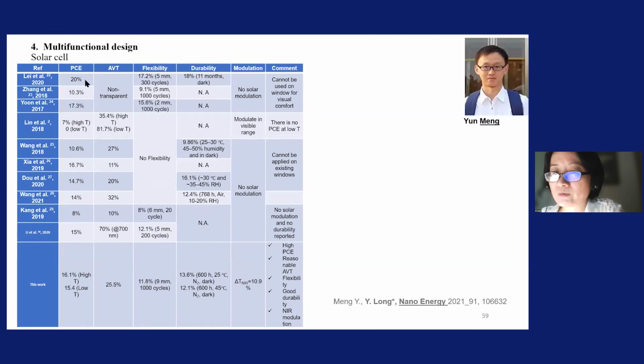We reported that if it's only a transparent solar cell, the PCE is roughly here. AVT is average visible transmission. If the PCE is high, normally the AVT is low. For this one, which is a Nano Energy paper, you can see the AVT is high, but the problem is the PCE is low. And also nobody talked about energy saving before. They only talked about using it to generate electricity. But how about the heat incurred there? So you have to be very careful. There's no modulation at all.